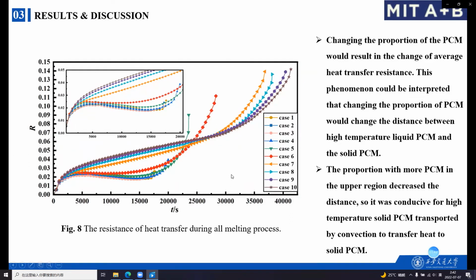This phenomenon could be interpreted that changing the proportion of PCM would change the distance between high temperature liquid PCM and the solid PCM. Because of the existence of natural convection, the high temperature liquid PCM always exists in the upper region of the heat storage, and the proportion with more PCM in the upper region decreases the distance. So it was conducive for high temperature liquid PCM transported by convection to transfer heat to solid PCM.